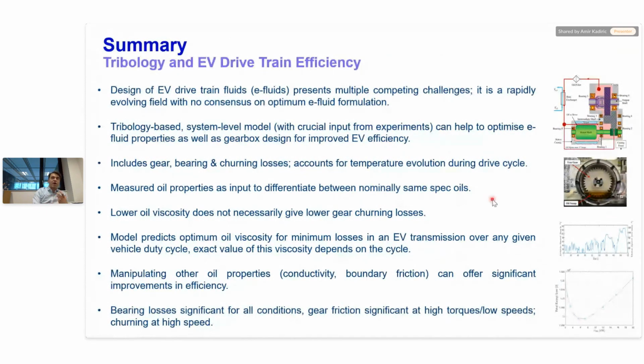Crucially, we don't just rely on modeling. We include the oil properties measured in our rigs so that we can tell the difference between two similar or same oils. And I've illustrated the fact that we can. And I think our results then show that there is indeed an optimum for any vehicle duty, and that optimum is dependent on that vehicle duty. So one for WLTP, one for a harsher, one for a less harsh cycle. But the nice thing is that there is an optimum.